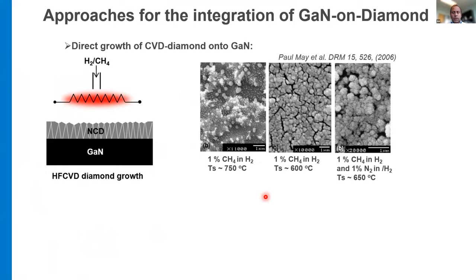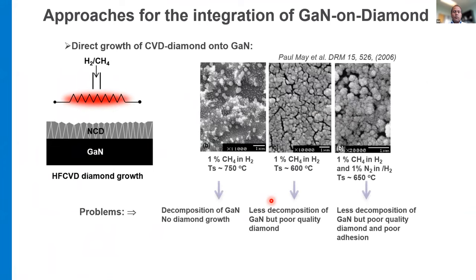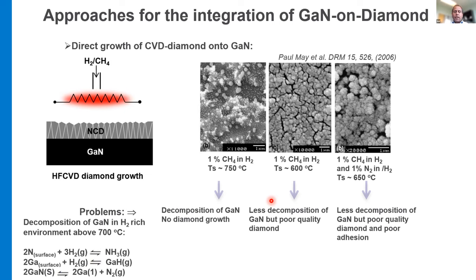including the conventional CH4 and hydrogen chemistry. The problem here is, of course, even though the gallium nitride can withstand higher temperature, in a hydrogen atmosphere, where you have more atomic hydrogen present, that starts to attack the gallium nitride, and there is a reaction with the gallium, and you start to lose the nitrogen from the gallium lattice, and then there is a decomposition of gallium nitride at higher temperature. So they tried to deposit at a lower temperature, 650, but then you get a very poor quality diamond film with less adhesion, and that's why the direct integration of diamond in the CVD process has these problems.